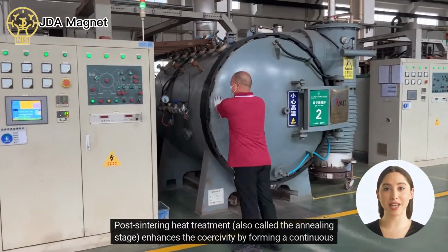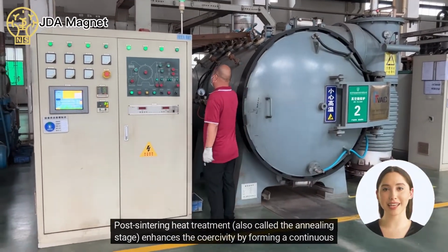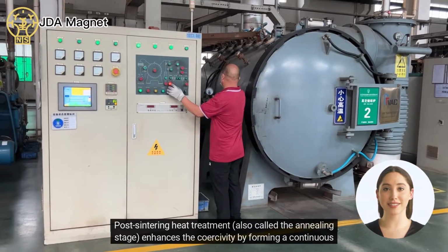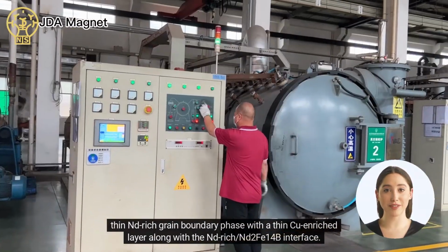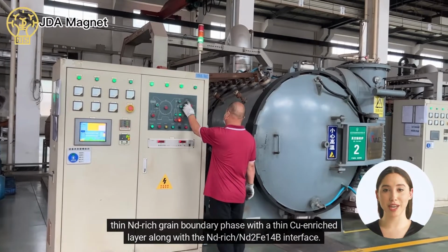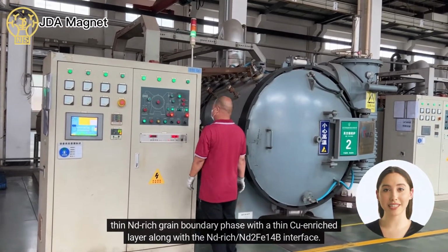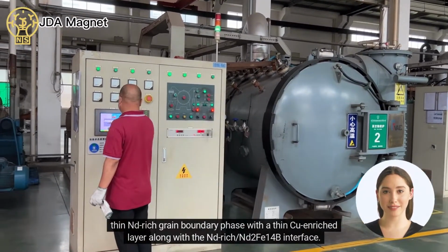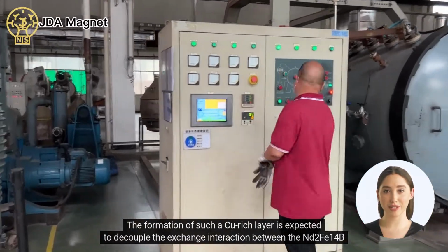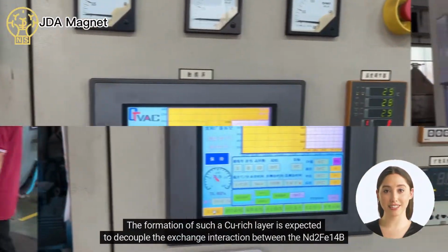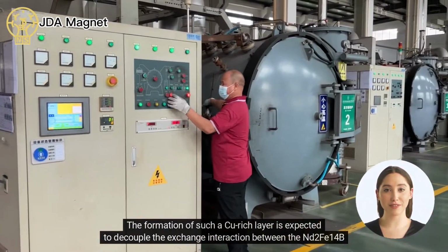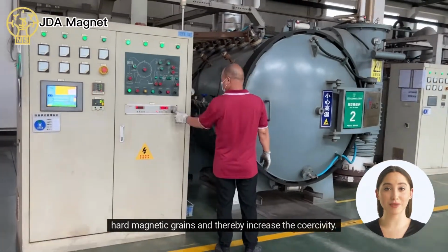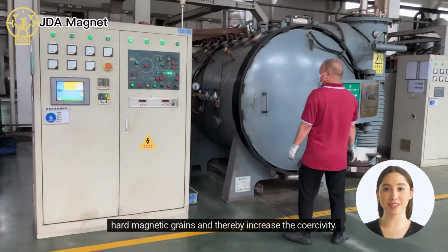Post-sintering heat treatment, also called the annealing stage, enhances the coercivity by forming a continuous thin Nd-rich grain boundary phase with a thin Cu-enriched layer along with the Nd-rich/Nd2Fe14B interface. The formation of such a Cu-rich layer is expected to decouple the exchange interaction between the Nd2Fe14B hard magnetic grains and thereby increase the coercivity.